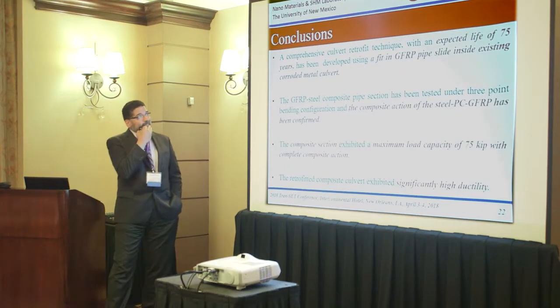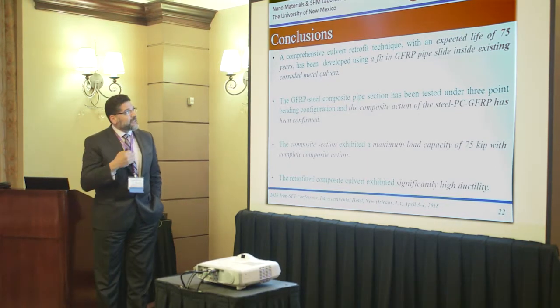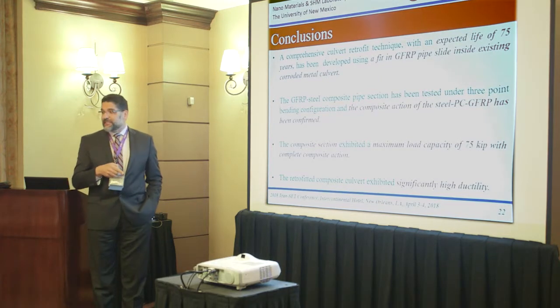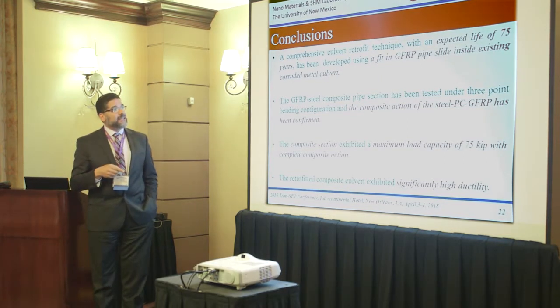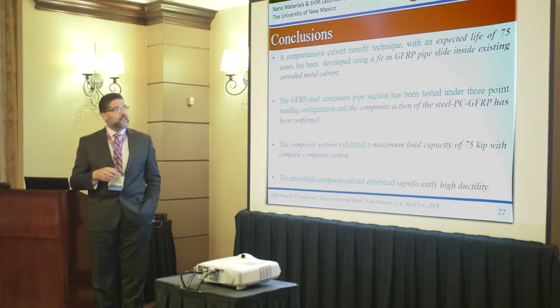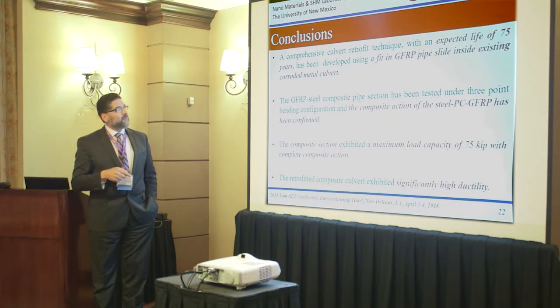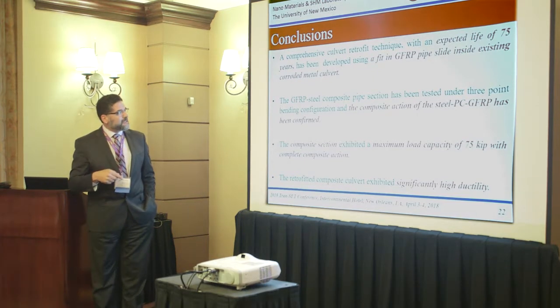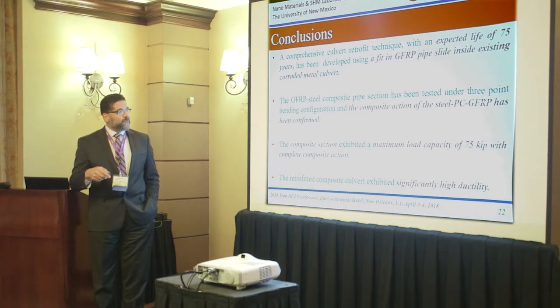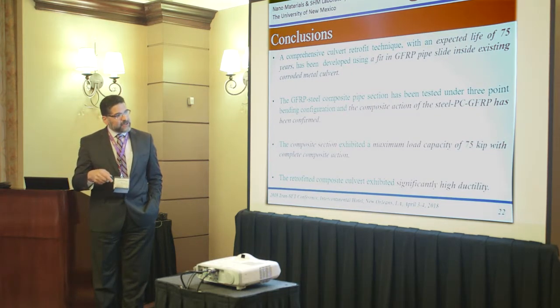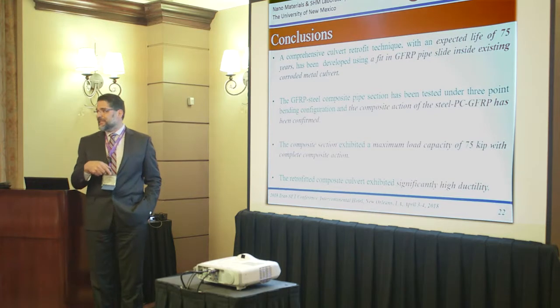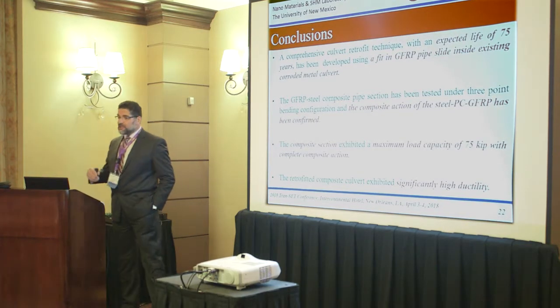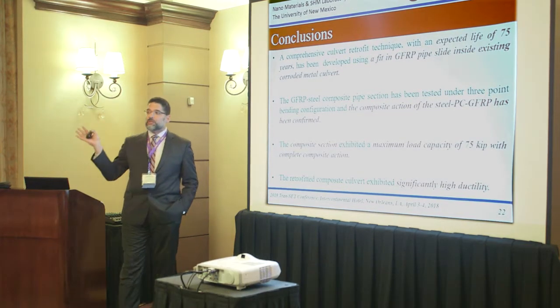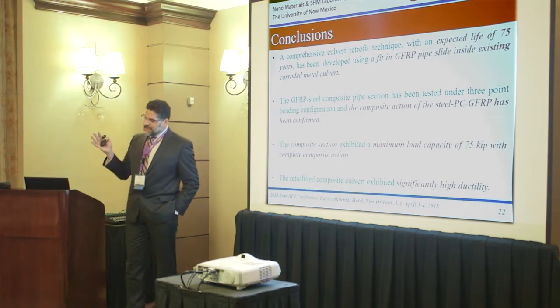So in conclusion, we believe we have done a reasonable and comprehensive retrofit technique that shows that we can increase the expected life to 75 years by using a GFRP pipe or profile slid inside the corroded metals. Composite action is confirmed. The composite section reached a maximum load capacity of about 75 kip with significantly high ductility that you wouldn't see with others. The polymer concrete did not fail, and there was no debonding, which is great.